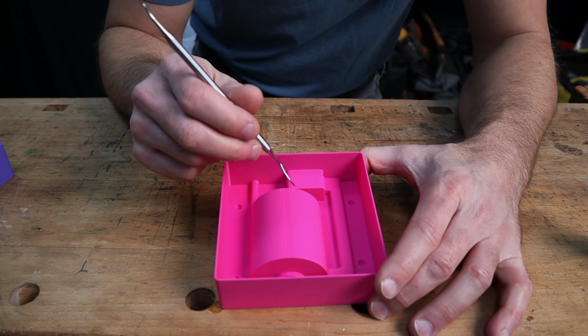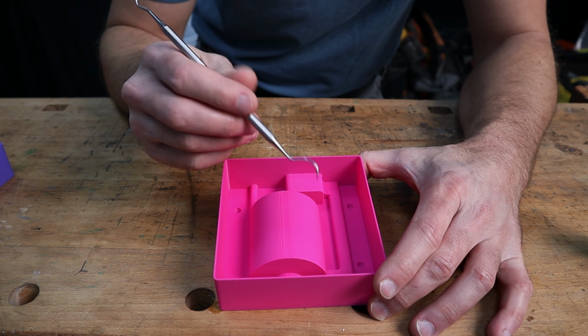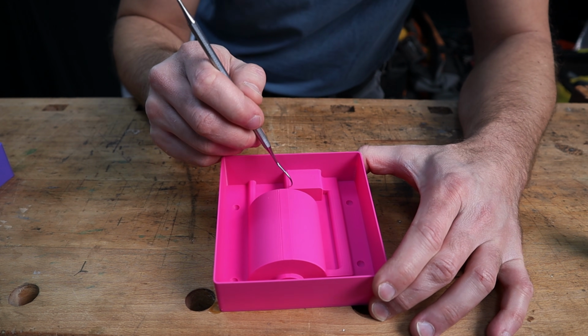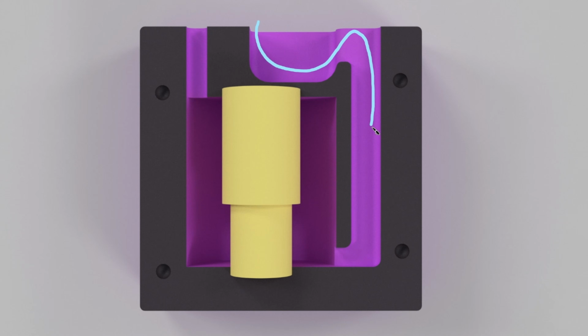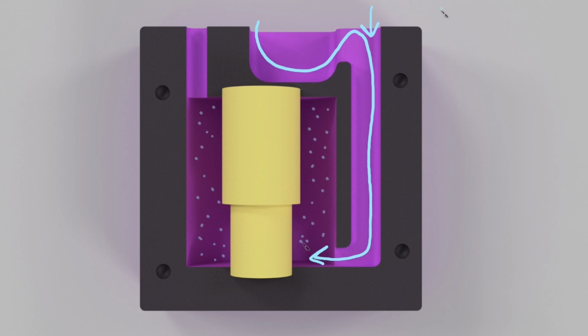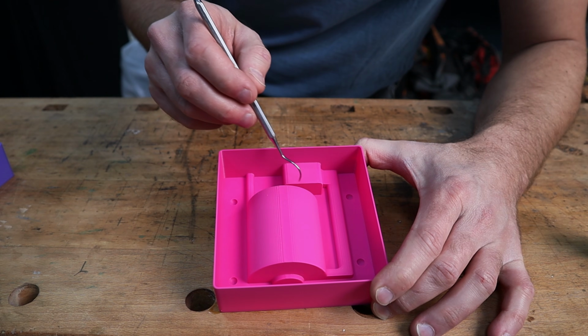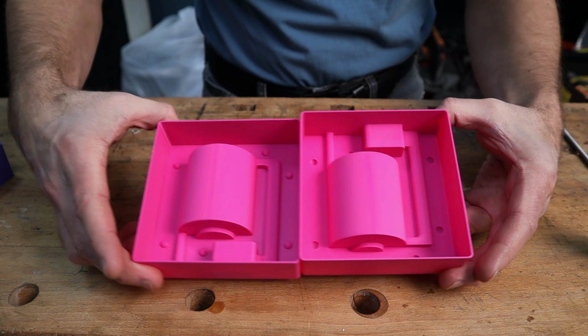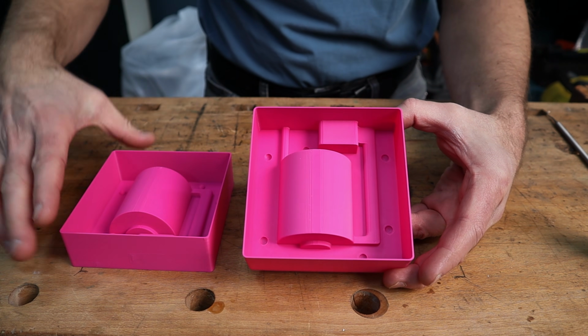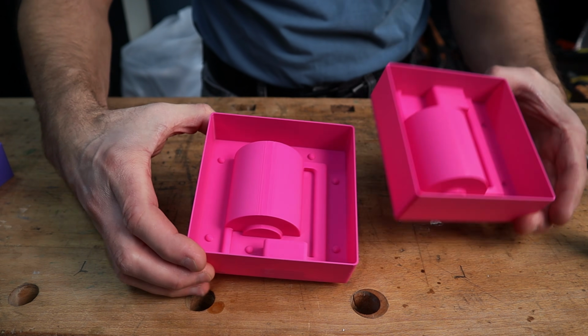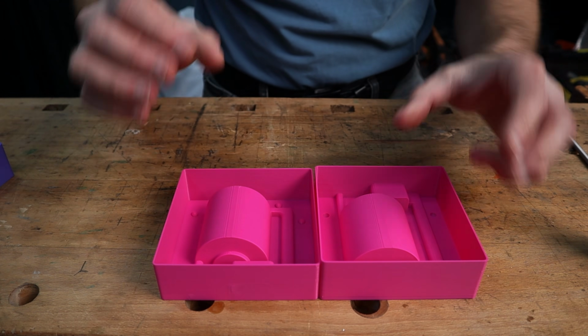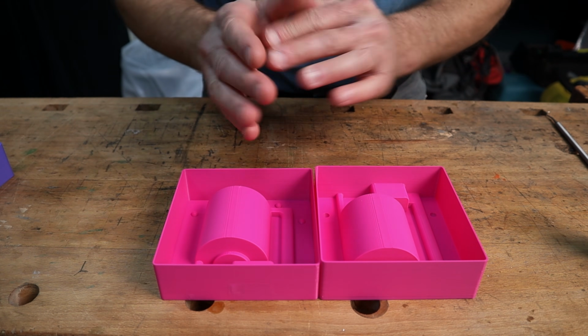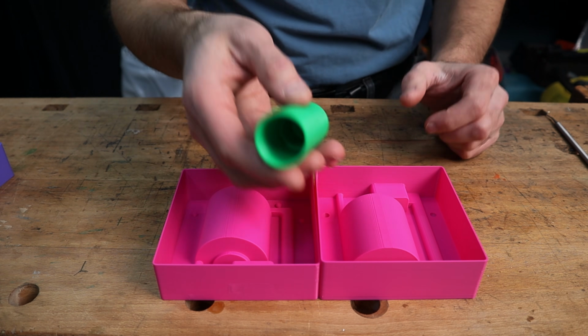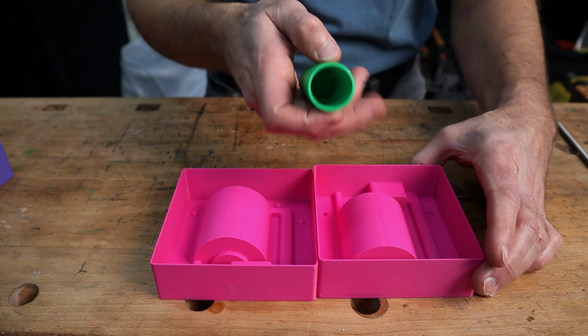And then another area I focused on was the pouring basin. If we had a pouring basin that was curved, as we're pouring the molten metal in, it's going to want to swoop in and bring some air into our part. We don't want that at all. So instead, we want to leave these crisp, sharp corners. It's going to create some turbulence. And we have the two parts, and there are some alignment pins there as well. Everything is designed so that there's a little bit of clearance where the parts need to come together. I don't want to have an issue where the core doesn't fit properly into the mold.